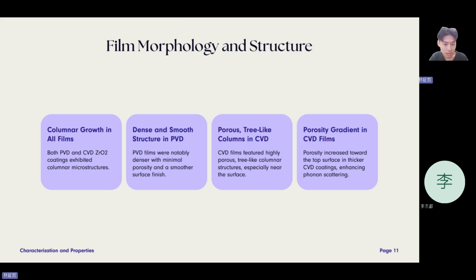On the other hand, the CVD films have a porous, tree-like columnar structure. They have many tiny holes. Also, in thicker CVD films, there are even more holes near the top surface. These holes are actually very helpful for blocking heat.